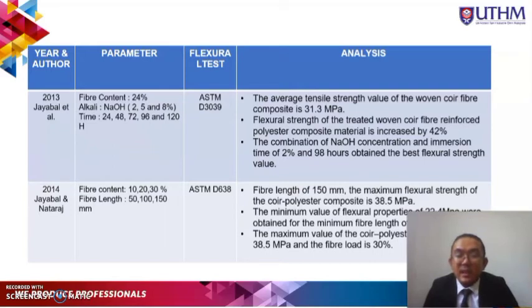Lastly, Jayabalan and Nataraj found that at a fiber length of 150 mm, the maximum flexural strength of coir fiber composite is 38.5 MPa. The minimum value of flexural properties, 22.4 MPa, was obtained from the minimum fiber length of 50 mm. The maximum value of coir fiber polyester composite is 38.5 MPa and the fiber load is 30%.